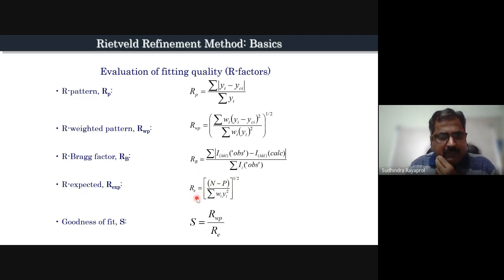If your data quality or number of points or number of parameters being defined is different, or if the quality of signal is very poor, then you will end up with a very high R expected value. And the goodness of fit is basically the ratio of RWP and R expected. Okay, so RWP being low and R expected being high will give a false minima. It cannot be less than 1. Because the R expected is the lowest value RWP can go. It cannot be less than that. So that is something we have to keep in mind when we work with our refinements.